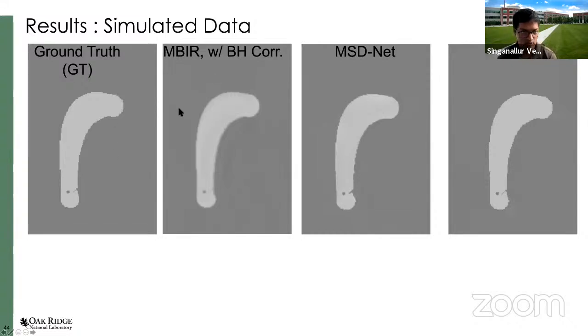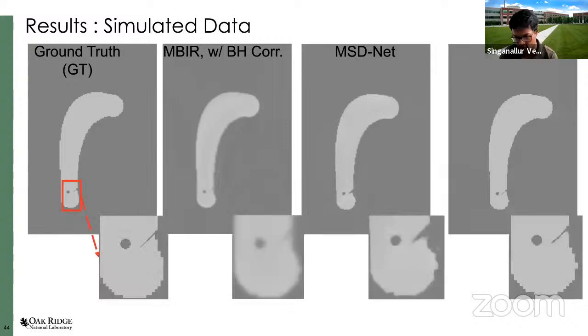We had some data generated, and this is the model-based reconstruction methods of the first part, which are time-consuming. And when you put in more sophisticated models, in this case, we do a two-step beam hardening correction and then reconstruction. It does a reasonable job, but with these neural network techniques, we can get a pretty good result, again, from these sparse view data sets from the CAD models. But this is still, of course, all simulated.